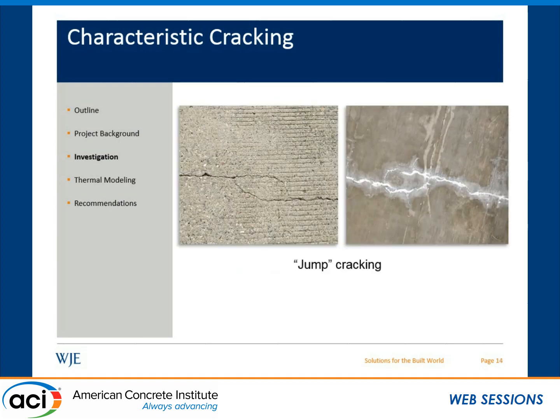The most interesting type of crack pattern we noticed is what we're calling jump cracks. And what these occurred, or where these occurred, were where 2 parallel transverse cracks were very close to one another, typically about 6 inches or less. And it ended up that the crack from one transverse crack intersected the other. And they formed what we're calling these jump cracks. And when these jump cracks intersect like this in the figure, on top and bottom, that's where we suspect the holes that we had seen formed.